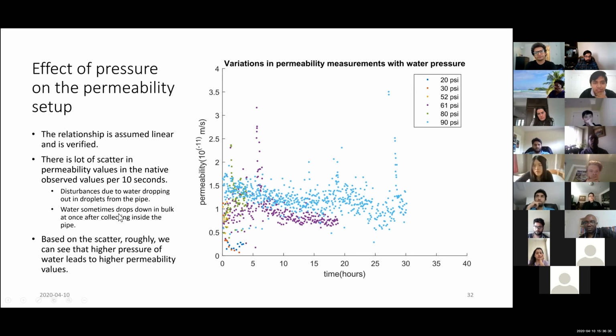What I found while I was doing the experiment is that the reason for this scatter is basically that the water drops out in droplets from the pipe, and so it's not a continuous drop. It drops out in discrete quantities, and sometimes there is a surface tension inside the pipe which holds back some of the water until there is enough water to go past this tension and fall in the beaker. So sometimes water drops down in bulk, so that's why sometimes we can see that there is a lot of water coming out. So these are those abrupt values, where water drops all at once. And roughly we can see that higher pressure leads to higher permeability.